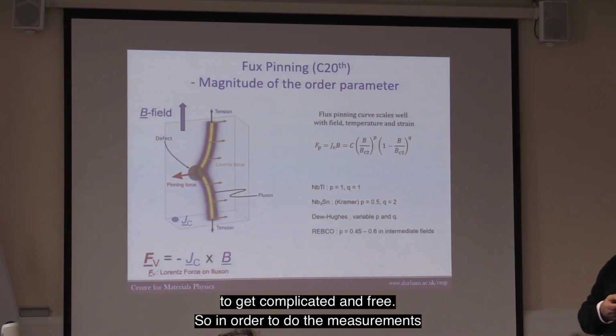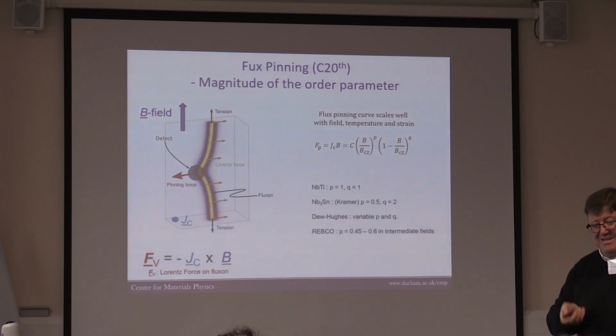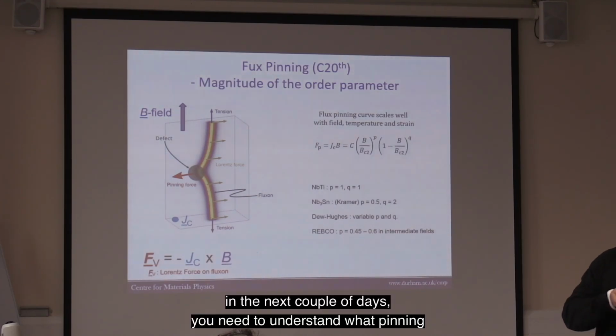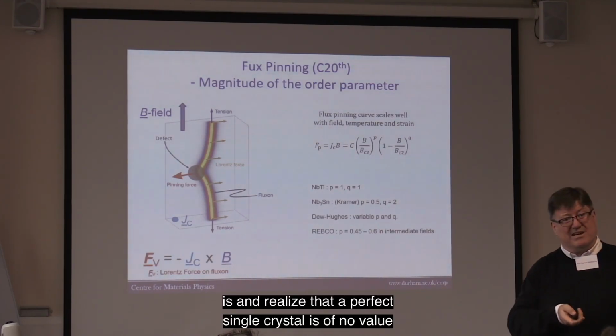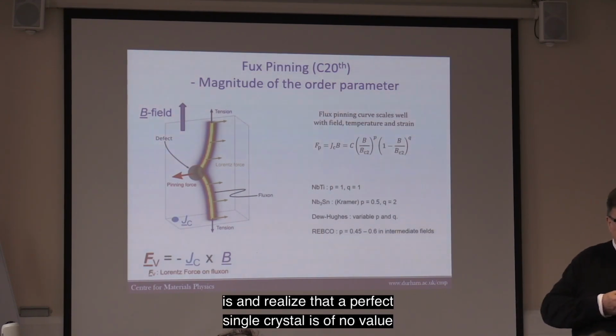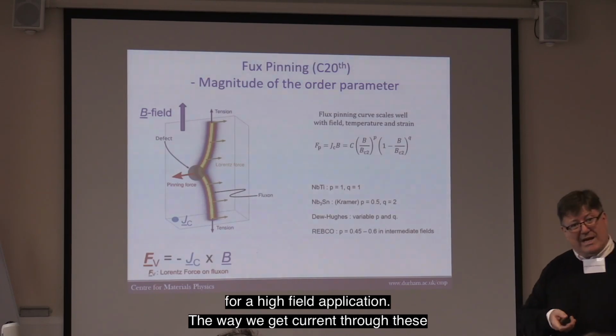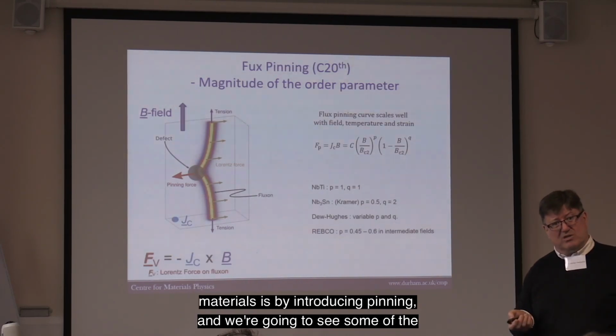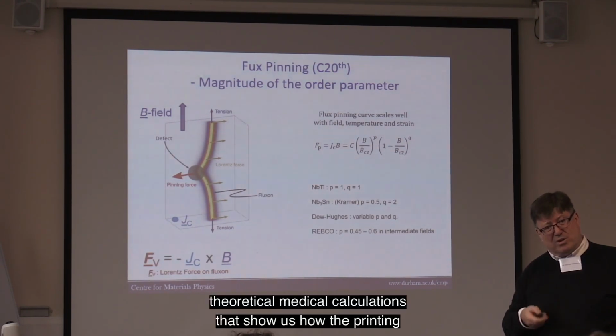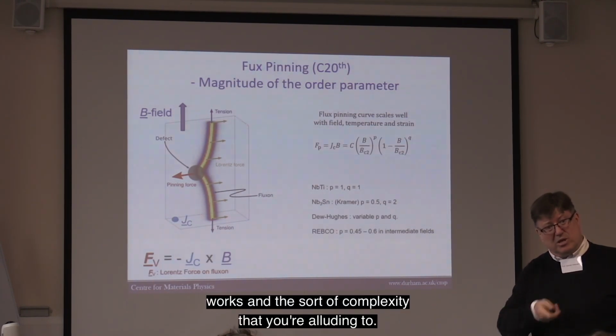In order to do the measurements in the next couple of days, you need to understand what pinning is and realise that a perfect single crystal is of no value for a high field application. The way we get current through these materials is by introducing pinning, and we're going to see some of the theoretical calculations that show us how the pinning works and the sort of complexity that you're alluding to.